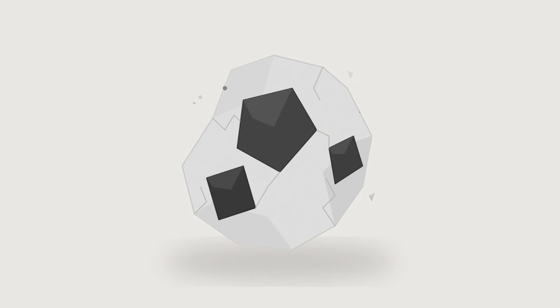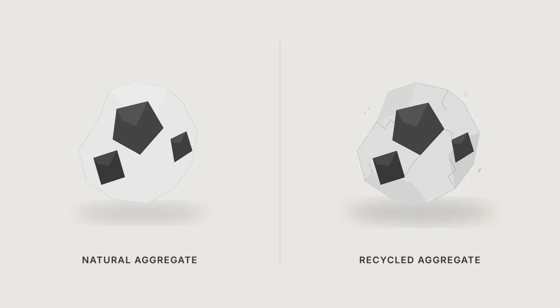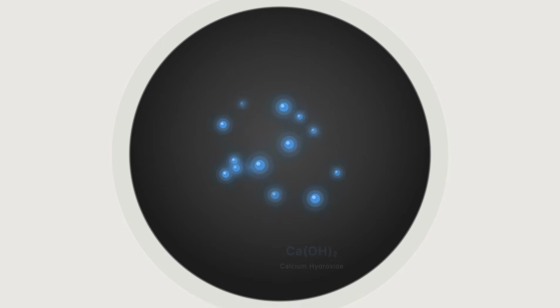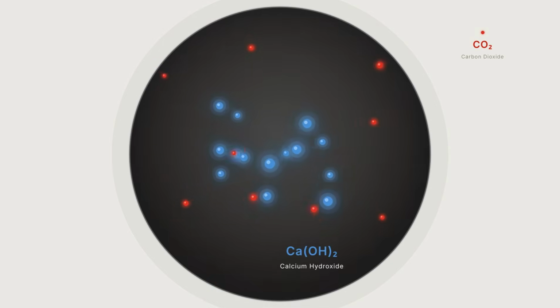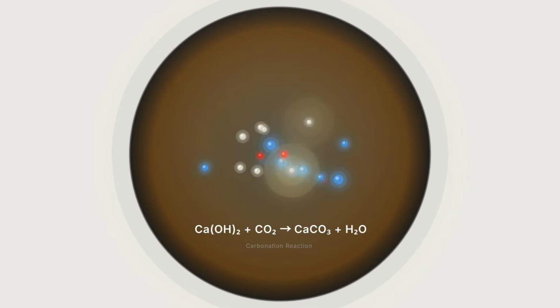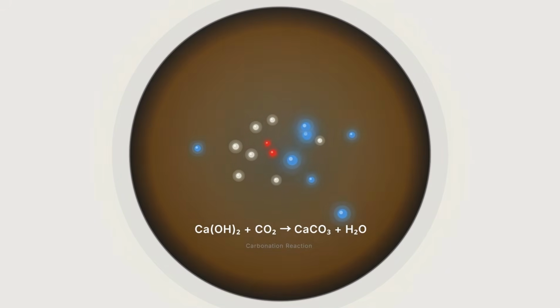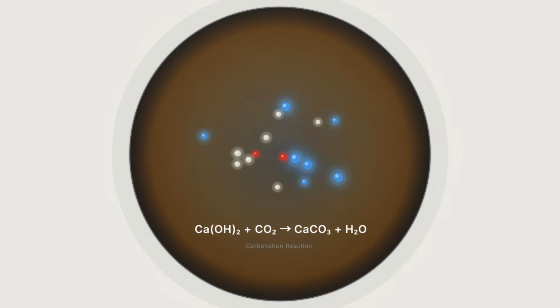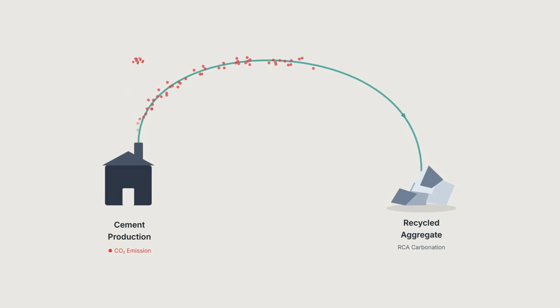Residual mortar stays attached to its surface, making it more porous, more absorbent, and weaker than natural aggregate. The important part is this: that old mortar still contains calcium hydroxide, so the weakness also becomes the reaction site. This is where RCA and carbon capture combine. The carbon dioxide released earlier by the cement can be sent back into the recovered concrete.